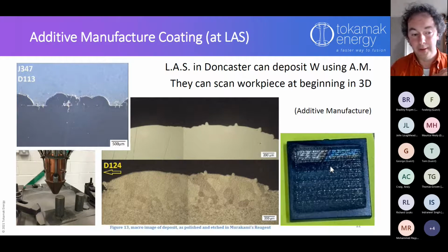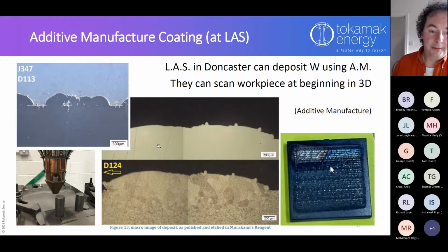So that's the aim. We've taken the sample, and then what you do is you put a layer of tungsten on top of that, so you now have a surface that you've made with laser additive manufacture. So in theory, once we get this to work, then you can make any shape you like. So you could take a copper heatsink perhaps and put the tungsten on the top as some kind of armor, or you could take some sort of steel, put tungsten on again to protect the surface, and you can make any shape you like.